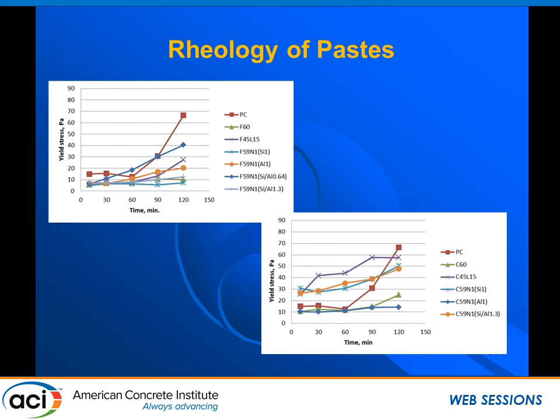So if we plot yield stress over time, we see that for the PC mix, there's a jump between 60 and 90. So something is happening in that time period.